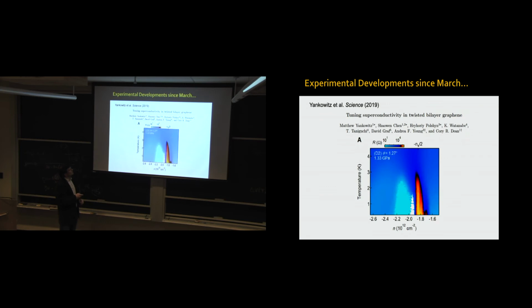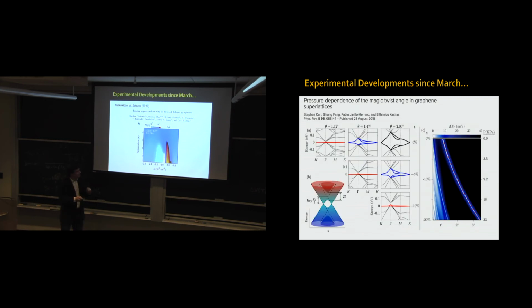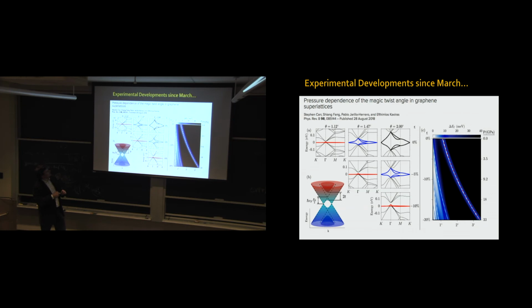The one published just a few weeks ago in Science was by the group of Corey Dean, in collaboration with Andrea Young. Not only did they reproduce our results, they also extended them in a very interesting way. I told you before that the magic angle condition depends on the interlayer coupling between the two graphene sheets. So my Harvard theory colleagues and myself predicted the following: if you have an angle which is not the magic angle, a bit larger, and you can somehow increase this interlayer coupling, you may make that angle be the magic angle, because it will have the right angle for a given interlayer coupling to develop flat bands.